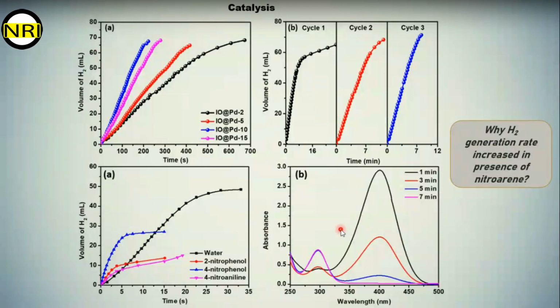This is because the hydrogen generated in this ammonia borane hydrolysis is used for two reactions. Water takes some of the hydrogen and forms hydrogen gas, and some of the hydrogen is used for this nitrophenol reduction. So when this hydrogen species is scavenged by the nitrogen compounds, it accelerates the hydrogen generation reaction, and that is why the rate of reaction is higher for the nitro reduction than for the hydrogen gas generation.